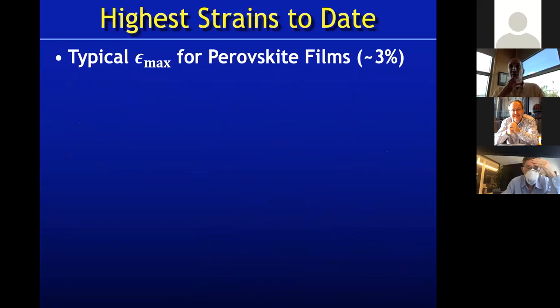Now, I want to leave you with some guidelines on how much strain can be imparted. This is a very powerful tool. And I've talked about the different things that can go wrong, the different ways that nature can respond and find energetically less expensive things than straining your film, and how that trades off with, of course, the thickness of the film. What's common in perovskites, as a rule of thumb, is that 3% is about the max that you can get in a lot of different perovskite systems.